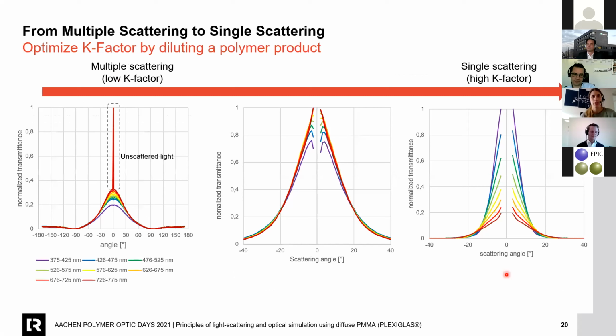On the next slide, you see three measurements of our dilution series. On the left, you have a real product with a low K factor, so you have a high concentration, and you see the multiple scattering of the product. Around 0 degrees, you have another effect: the unscattered light of the light source of our goniometer. Here, photons go through the sample without any scattering. Now we have to decrease the concentration of scattering particles and go to the diagram in the middle.